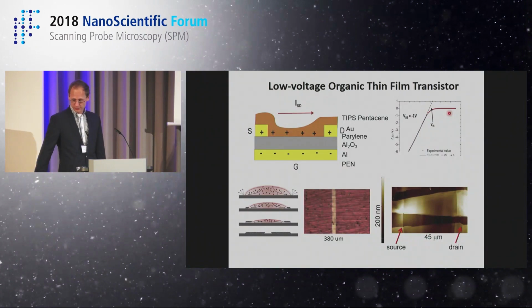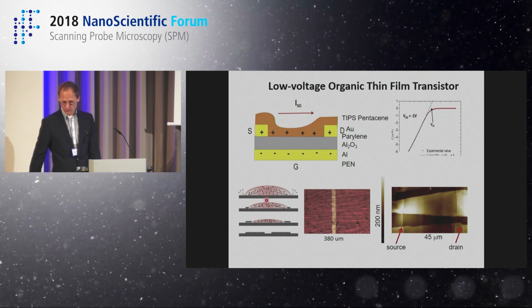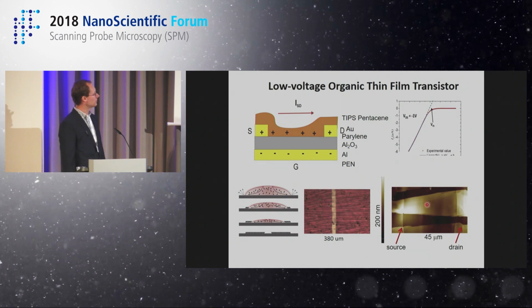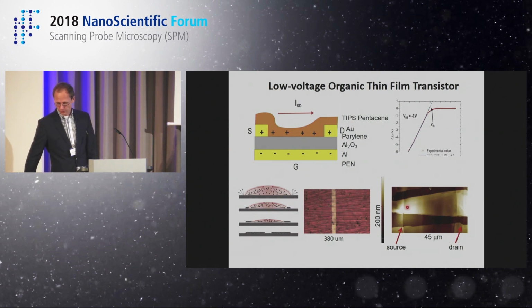With organic electronics, you would deposit such a semiconducting layer using an ink. So basically you deposit small droplets, the solvent evaporates, the molecules deposit on the surface, and they arrange into small nano or microcrystalline structures that are shown here. In violet you have the electrical contacts, and the gap where you have the semiconducting channel is shown here in yellow. This is my first AFM image, just the morphology of such a single crystal to show you how it bridges the source and drain electrodes.